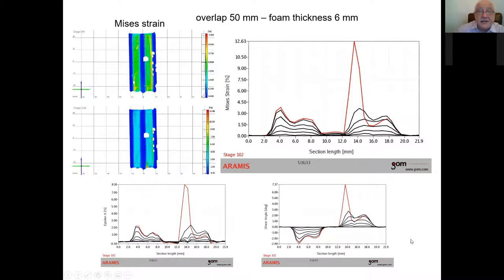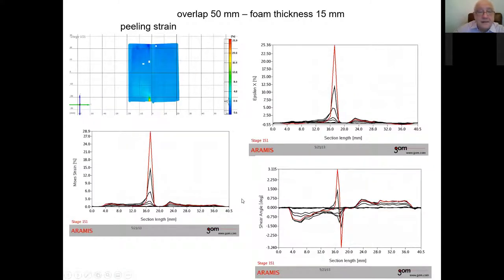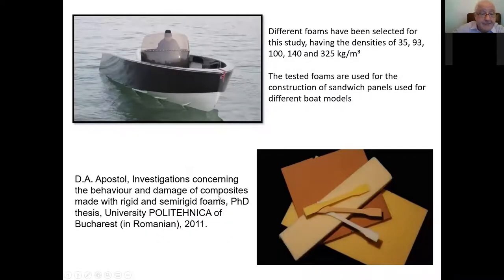Essentially, using this method, you can have quite precise measurements. Here is the upper case of 50 millimeter overlap. In this case, you had some damage starting from here, this interface on the right side, as you can see. Mises strain, this is along the horizontal axis, which is critical, usually in this location, again, close to the inner adherent, as you can see. So you can obtain nice reports, having the evolution of the strains at different moments, and of course it helps a lot. Well, another issue was on foams.